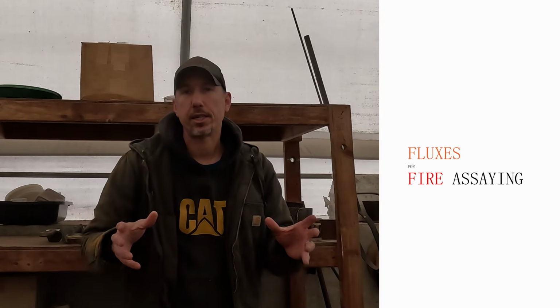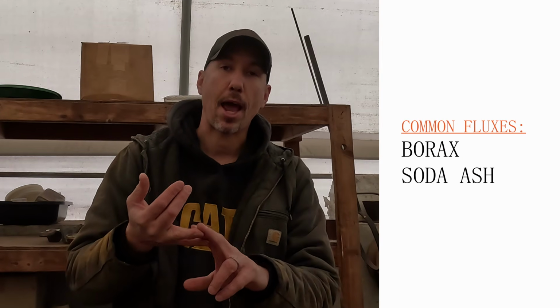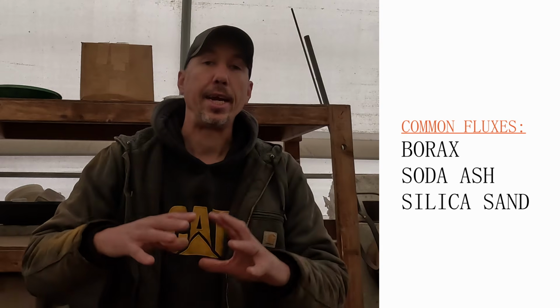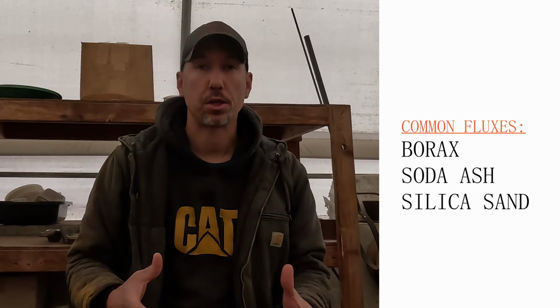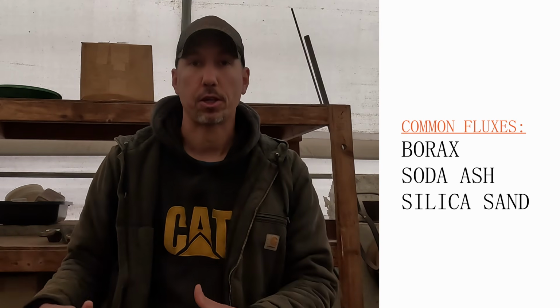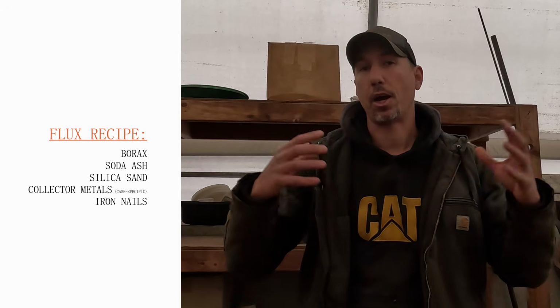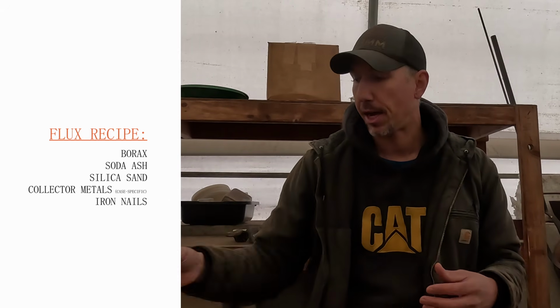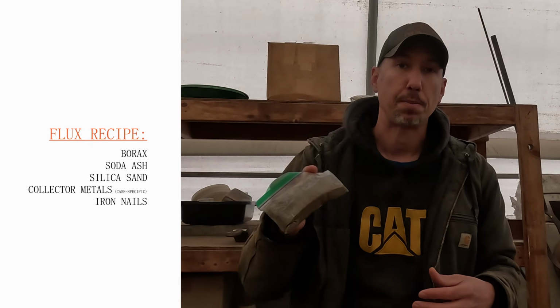There are 3 different types of fluxes that are very commonly used in fire assay. You have borax, you have soda ash, and you have silica sand. Each one of those chemicals does a different thing for our flux recipe. I've developed a standard high sulfide flux that I've used over the years, and I've had good luck with it across the whole gamut of sulfide high-grade cons, from my mine to other mines, and I'm going to use the same flux recipe with this stuff.